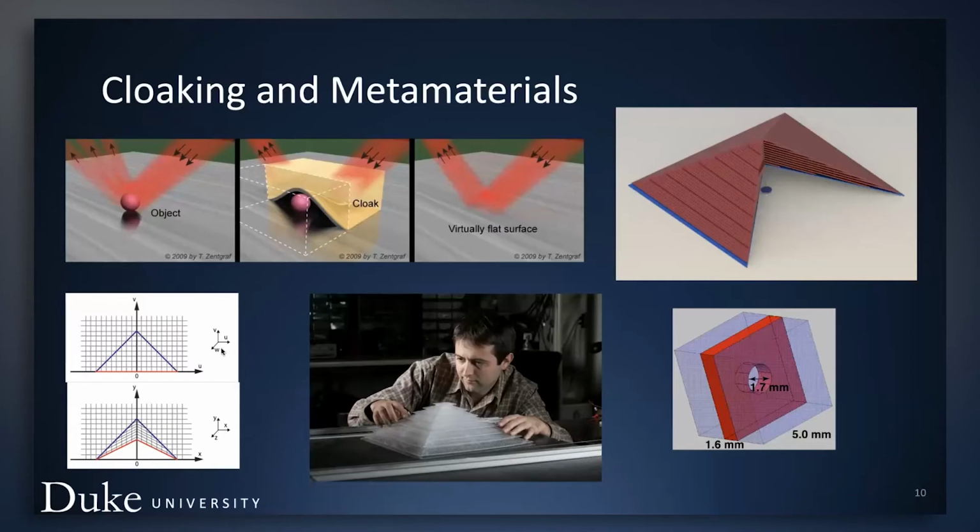What we did is we sat down, used the theory to describe what material properties we have to have for this shell, then used metamaterial design approaches to realize a physical structure that delivered those effective properties. And that physical structure is shown here, the one we built. Here's a cutaway version just in computer design. And all this is made up of is plastic plates with very precisely sized holes and very specific thickness to those plastic plates, and aligned along very specific angles in this structure. And there's open space on the bottom where you can hide an object.